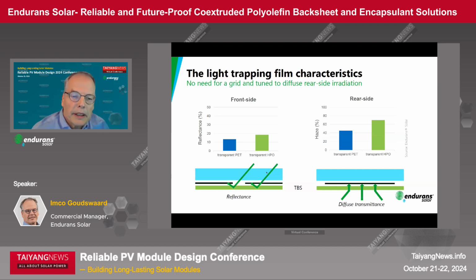This is the light trapping effect. On the left side, this is about light coming from the front. Like I said, the cell gaps are getting less and less. By including some reflection in our backsheet, we still have a good result in the front side flash test. But the main difference is obtained by making the film hazy, so it gets a diffuse transmission, and that is beneficial for the light which comes from the rear, because light from the rear never gets perpendicular. It's always scattered, diffuse, and with this high diffuse transmission, the light trapping effect of the film is much higher compared to a fully transparent backsheet. Next slide.